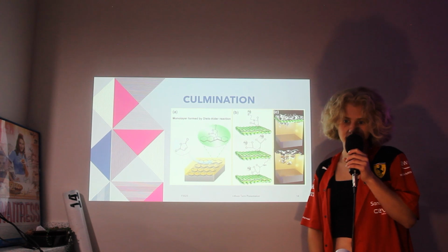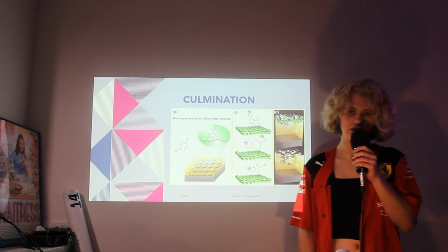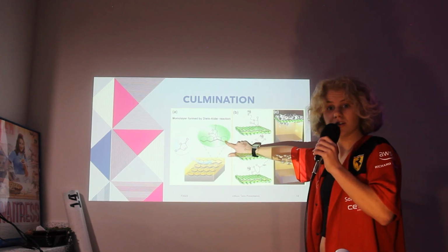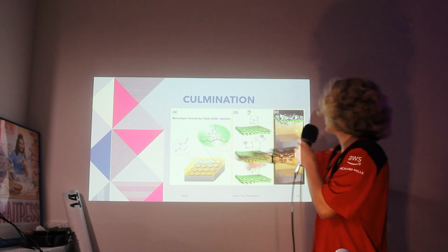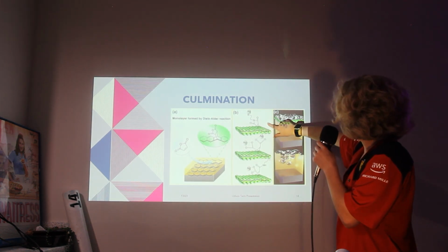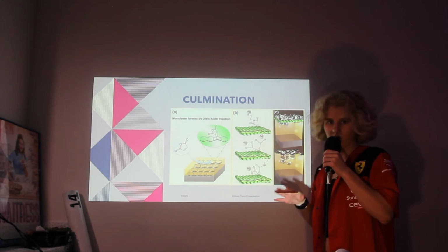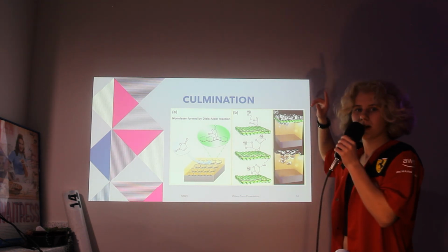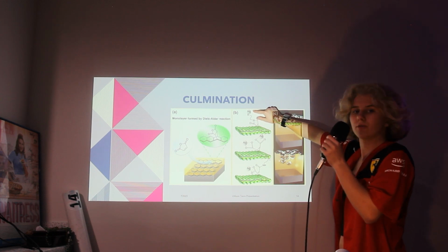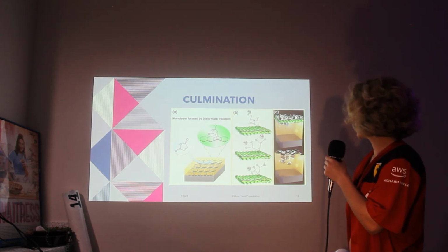of the silver layer, which makes the whole device more durable and also largely doesn't impact the quantum efficiency or conductivity of the material. You can see here that they did the same thing as in the last paper, in the sense that they made an anhydride and then reacted it with cysteamine, water, and N-butylamine, and then they used thermal deposition, so this is also a contact-based application, to apply the layer of silver for the cathode to the heteroatoms and to create these complexes.